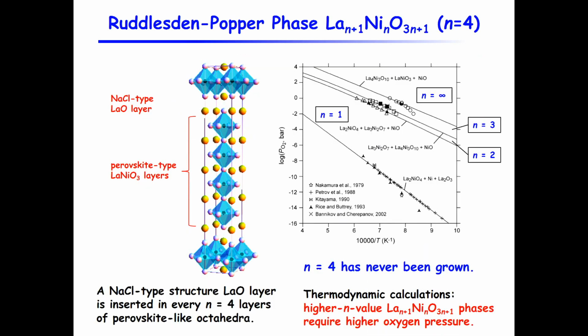And these, of course, are materials that are neutral. And we have also used it to grow polar materials like lanthanum nickelate. And we've grown lanthanum nickelate, this Ruddlesden-Popper phase with different n, right? So for this phase, for n number of perovskite type of layers, one more lanthanum oxide layer is added in it. And people have been successful in growing n equals 1, 2, 3, but nobody has reported n equals 4. And from the phase diagram, you can find that if you want to grow higher n value, you need higher oxygen pressure. The problem is, for every n perovskite layers, you want to add one more lanthanum oxide layer.